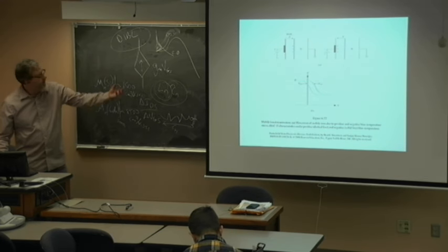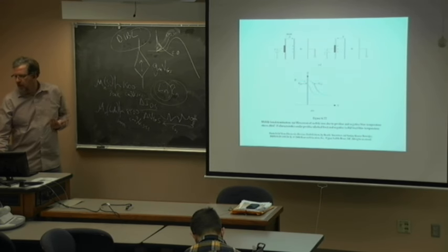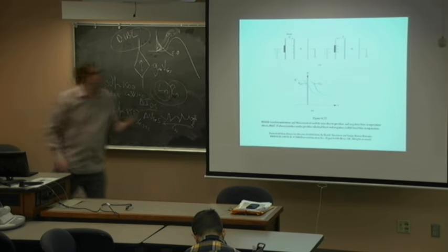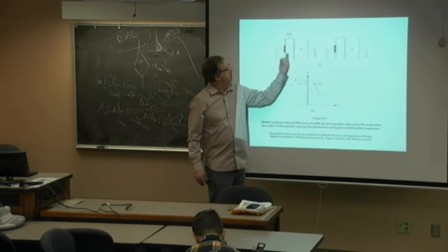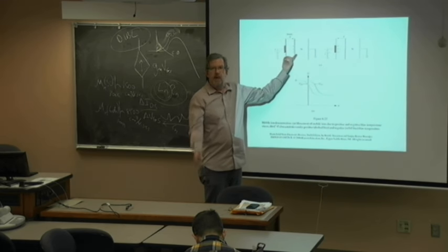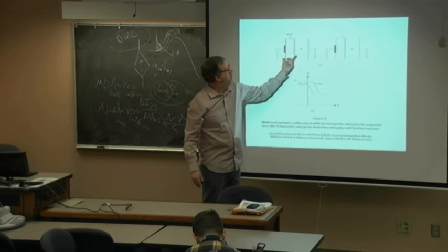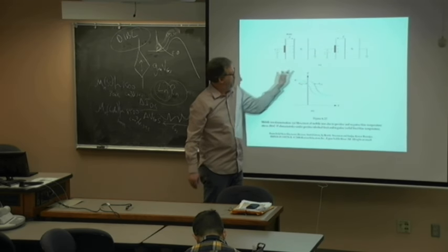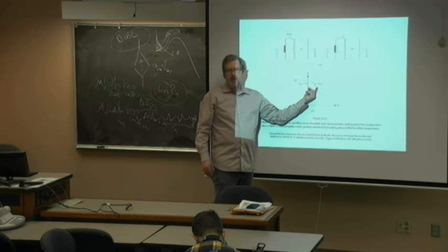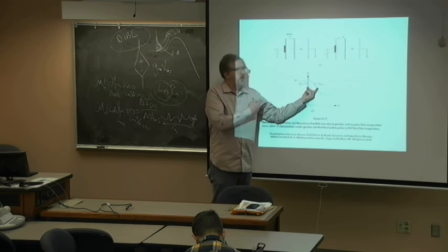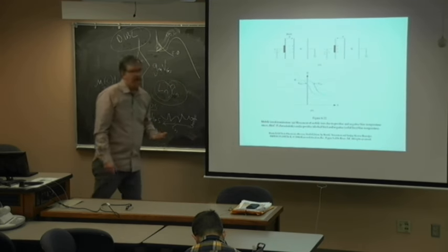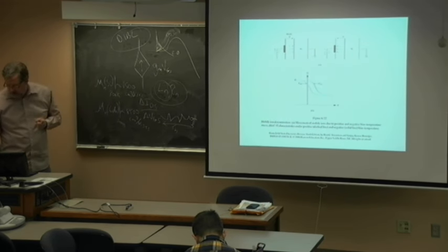Yeah, and then you can see the flat band condition moves back and forth with the bias. This sloshing around, by the way, is that mobile charge. So the mobile charge has sort of a hysteresis. It moves back and forth. That even has a memory effect from where it was biased before. So it's shifting that CV curve. So this shift allows me to electrically measure how much mobile charge I have. The shift is indicative of the amount of mobile charge I have.